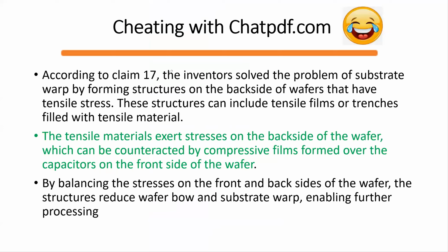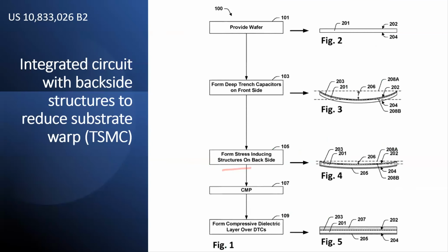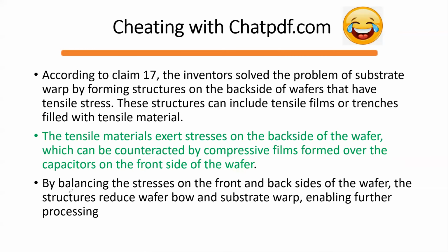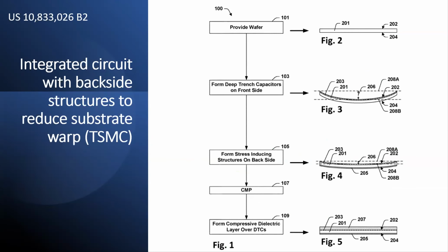I cheat again with ChatPDF. The tensile material exerts stress on the backside of the wafer, and the compressive layer forms over the front of the wafer. So the bottom one is tensile and the top one is compressive, and they do it in a way that will completely balance each other out. So I have a flat, stress-free wafer. That's a pretty good, decent idea. By balancing the stress on the front and back side of the wafer, the structure reduces wafer warpage. Nice.